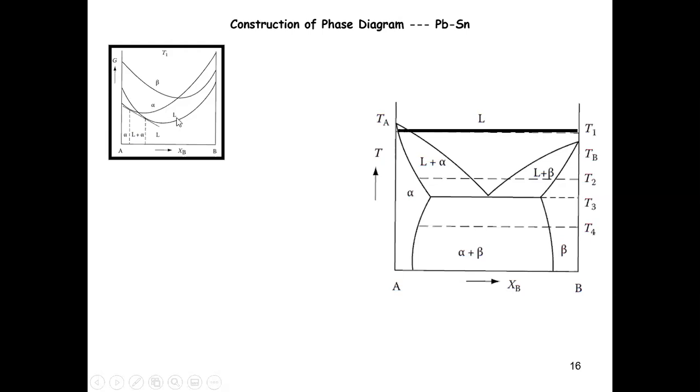So in this scenario, it's pretty much going back to the liquid and solid phase analysis we did before, because I'm only worried about two phases. So in general, there will be a region of composition where you have coexistence, right? And then for very low composition, your solid phase can dissolve this small amount of B in A. So the solid phase at this temperature can remain a solution, a single phase. And at a very high composition, the system is stable as a liquid, okay? Because B has a lower melting point, right? So if you dissolve A and B, you can dissolve them in a liquid state.